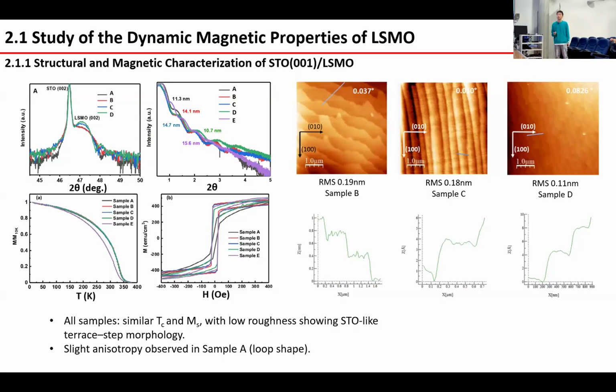And also the AFM image shows a quite clean, terrace-like surface with very low roughness and a really similar miscut angle as well. And also the DC magnetic properties are quite identical across the series of samples grown on STO 001. However, sample A in the low field shows a different kind of line shape compared with other samples, indicating a slight anisotropy different from other samples. So from this analysis of the structure and the magnetic properties, there's almost no change. So the dynamic property change of the LSMO maybe comes from other factors.